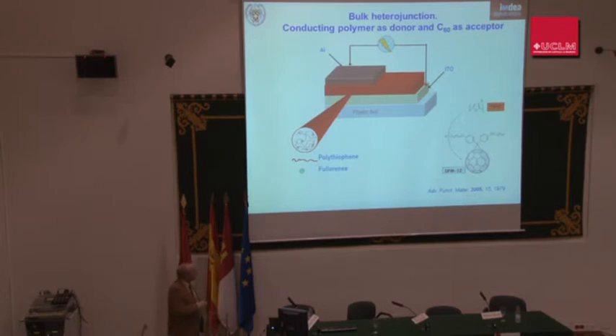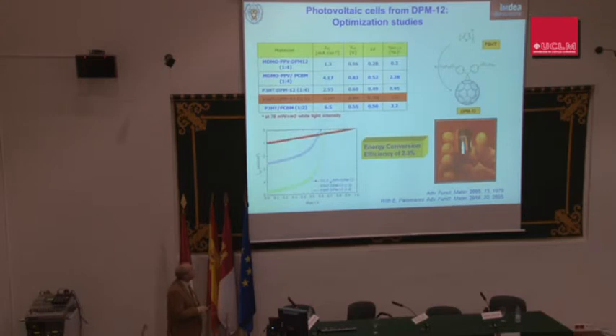Just by mixing the polymer like poly-3-hexylthiophene with the DPM-12, the device was prepared, and here you have some of the data. Many parameters should be considered at the same time. In particular, the stoichiometry is one of those parameters which are essential. Here you see the polymer and the fullerene derivative. Of course, this study was carried out by comparing with PCBM.